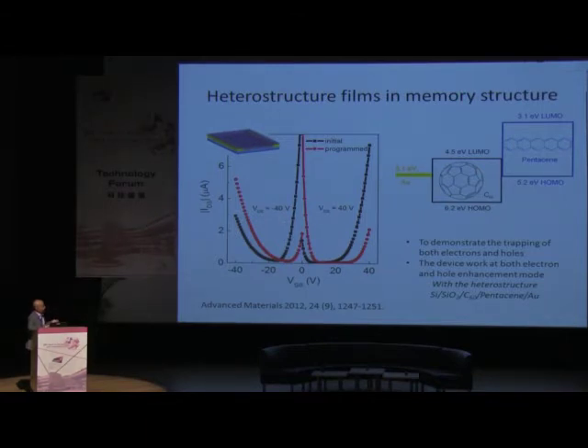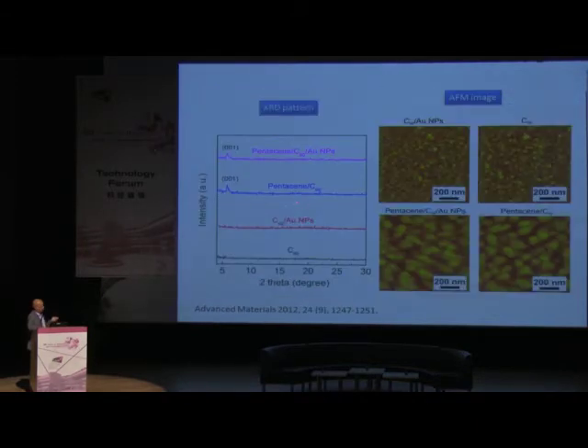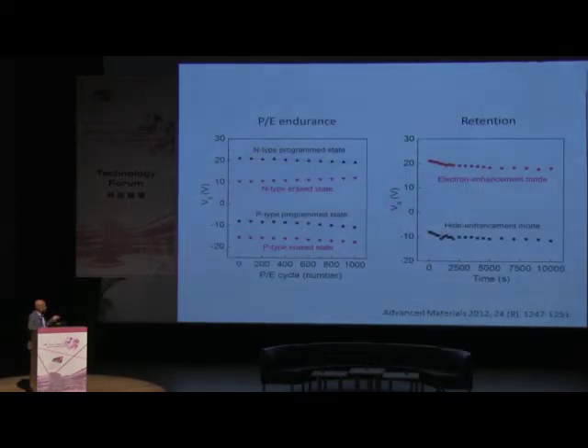So we start to think about how to trap both electrons and holes to have a larger memory window. First of all, we try to solve the problem of memory window, have more density. So we design a structure with two molecular materials, both of which can be solution processed, and with gold as electrode. You can see it works in both electron and hole enhancement mode. So basically you can trap both electron and hole in the device. And they form a beautiful crystalline structure on the surface. And you can program in electron and hole enhancement mode. Basically you can program electrons or you can program holes. So it works in both modes.